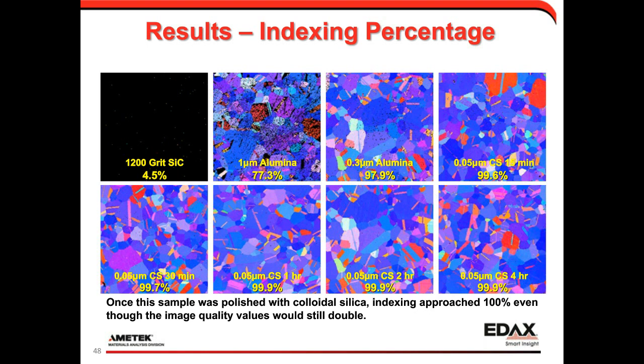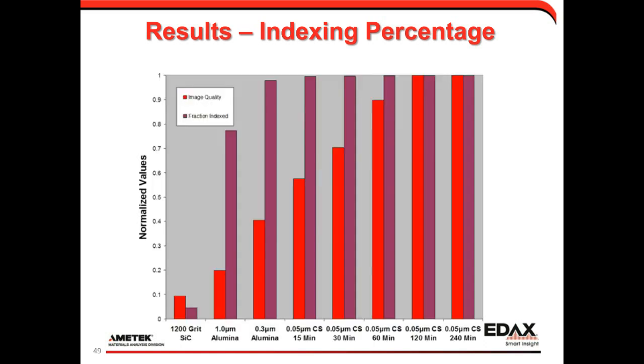So for a lot of our analysis, once we go to 15 minutes of colloidal silica, we're really going to get what we need for a lot of our microstructural characterization. Clearly, if we're just trying to measure grain size or texture or phase, a little bit of colloidal silica is probably going to get us pretty close to where we need to be. And if we put these on the same chart, you can see that with image quality, we didn't start plateauing until about 2 hours of colloidal silica. But if we look at indexing rate, we really are where we need to be with 15 minutes.